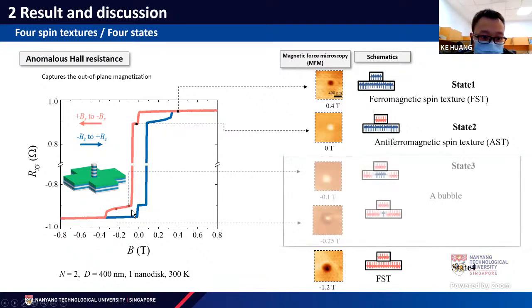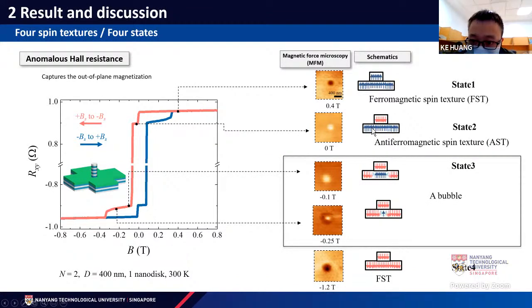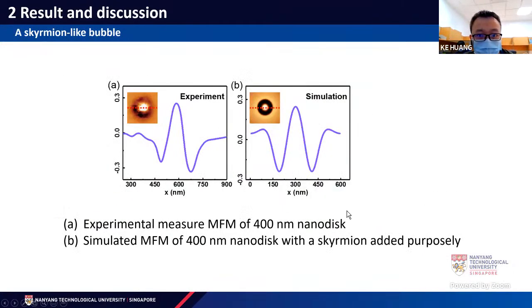After it crosses the coercivity, we can see that the spins in the bottom layer, which are not covered, are flipped. After it flipped, it has this kind of gradient transition from the center upwards, gradually transitioning to downwards toward the outer side. If we check this MFM image, the inside is bright and the outside is dark, so there are both bright and dark areas inside the nanodisk area. It's like a bubble. So we were trying to check whether the spin texture of the bubble follows the spin texture of the skyrmion.